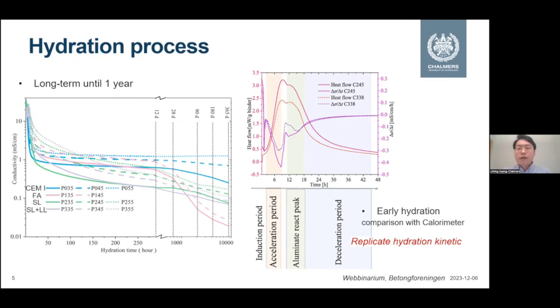For the long term, we can also collect data for longer than 1 year. Here I just show 1 year because it's data published in a journal, but now we keep the samples and have collected 3 years of data. It still works really well. I mean, the tendency really matches this curve. And we also see that after 1 year, the effect of fly ash can be clearly identified, or measured, by the electrical conductivity change.